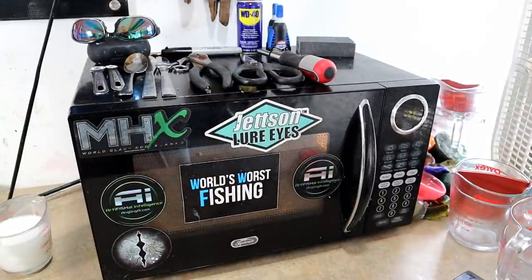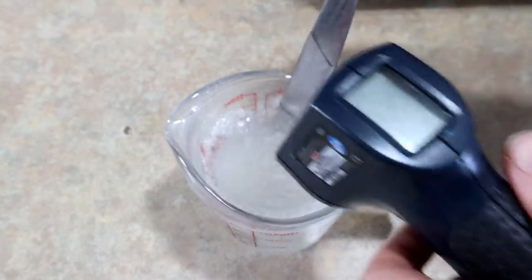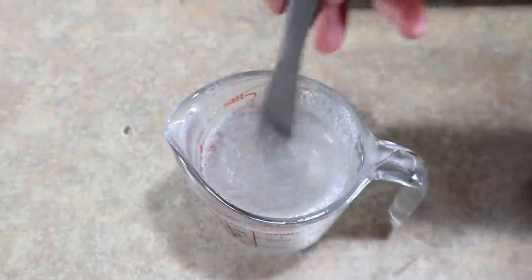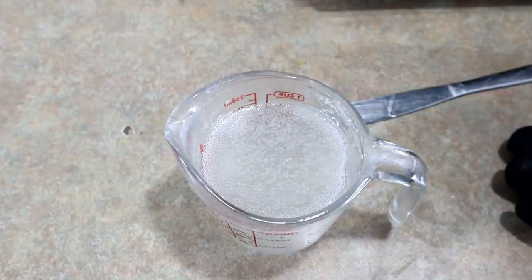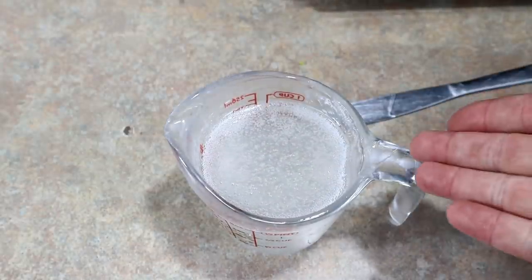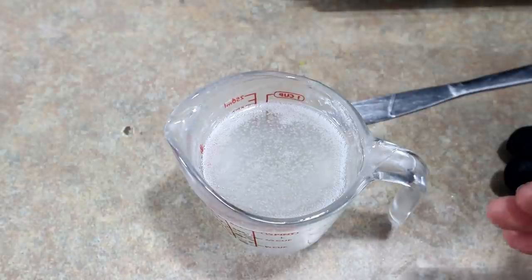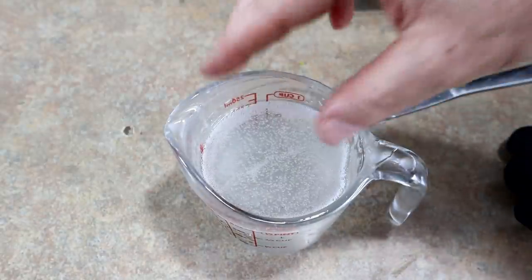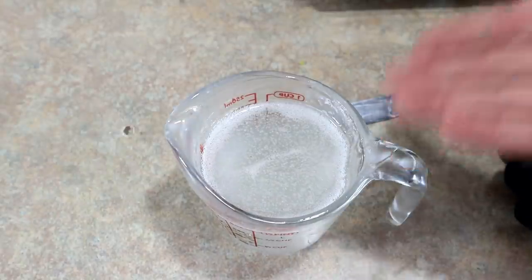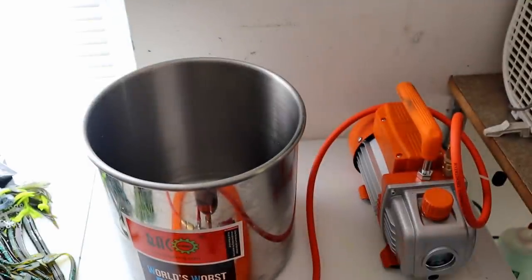So the same cup is going back in for about 30-second increments. That plastic is looking really good — 375°F — perfect. Our plastic is fully cooked. We've stirred a few little bubbles in, so we have two options: let the plastic sit and the bubbles will work themselves out in a few minutes, or use a vacuum chamber. For demonstration we're going to the vacuum chamber — this is the number one way to get rid of bubbles, whether your plastic is out of control or minimal like this.